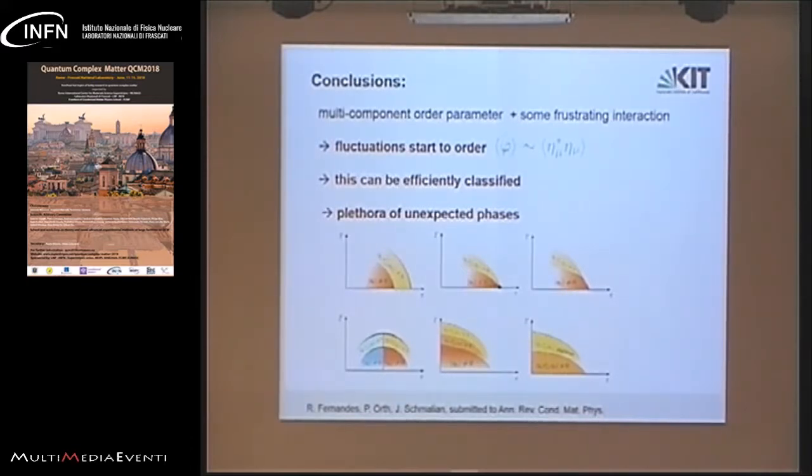The idea came from Ian Fisher, who proposed the measurement of what is called elastoresistivity. What you do there is you take the resistivity anisotropy as a placeholder for the order parameter of whatever is going on there. And you do the Legendre transformation of the theorist in the laboratory. You do it always at zero strain. So you tune your system to a situation where you do not have that deformation. Then you take the derivative, d order parameter d strain. If the order parameter was strain, the result would be 1.